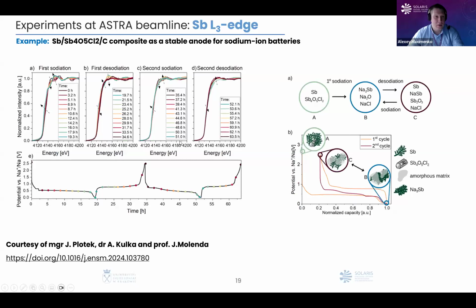And the last but not least example which I would like to show you was actually realized in the tender energy range at the antimony L3 absorption edge, and it was also realized in operando regime. It means that we had a battery which mimics the CR2032 battery, which we use in plenty of our applications, but we have windows in this battery from both sides,